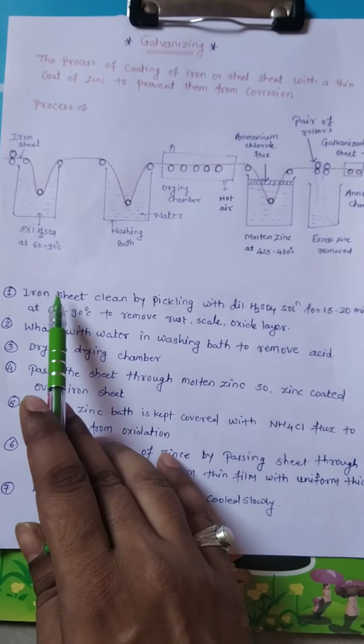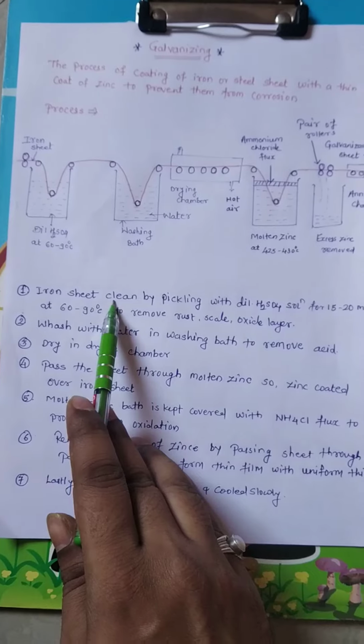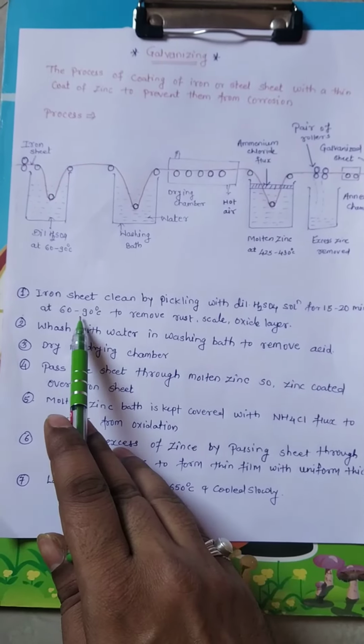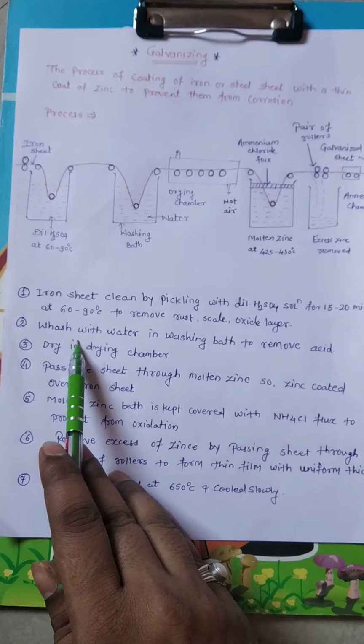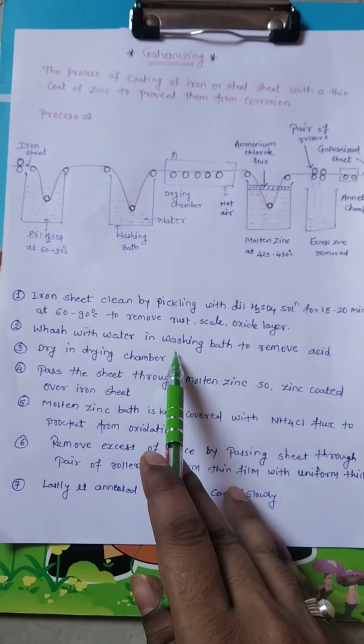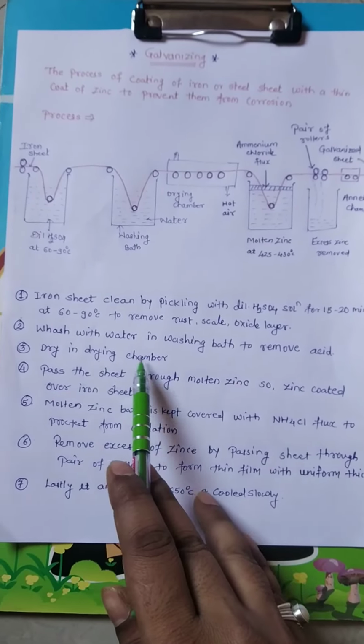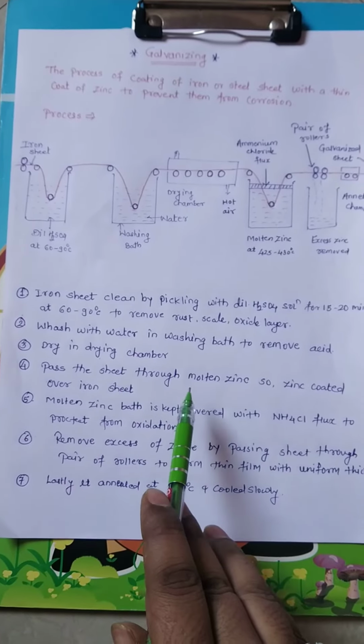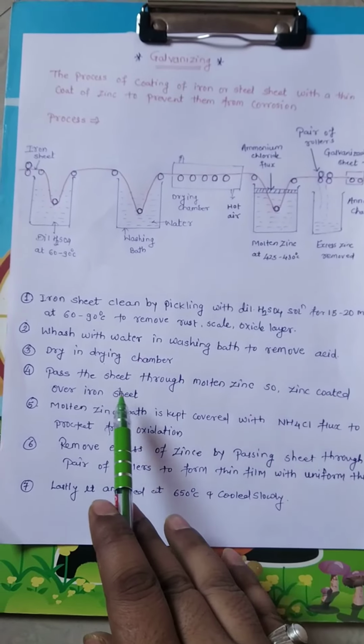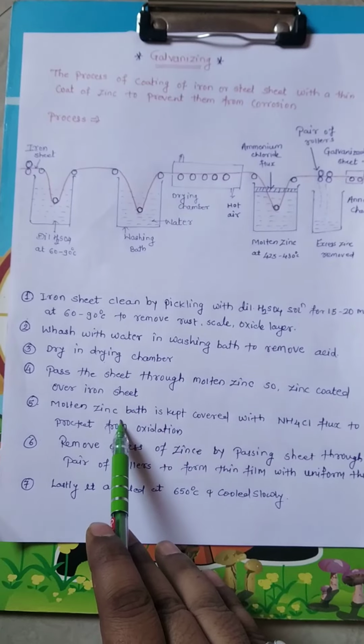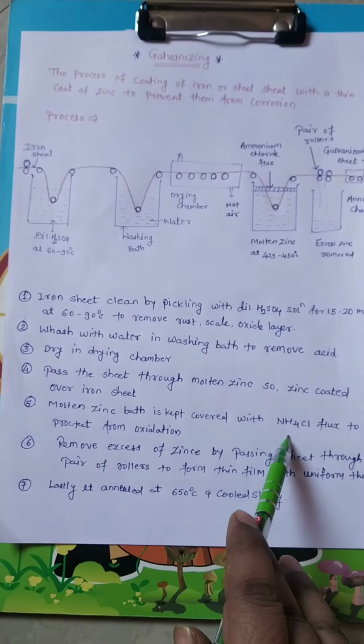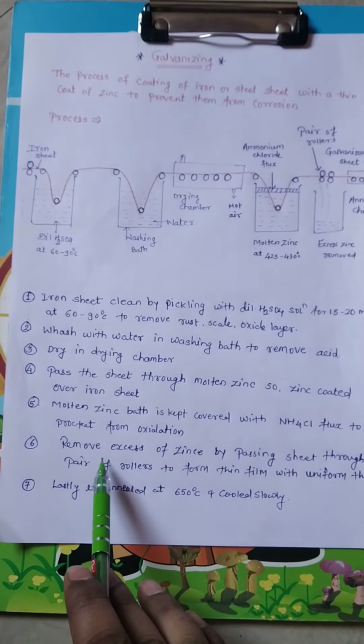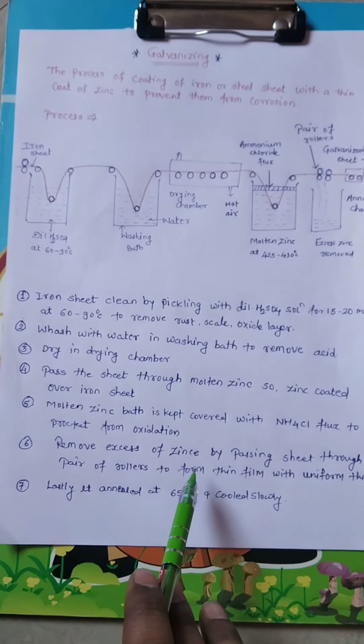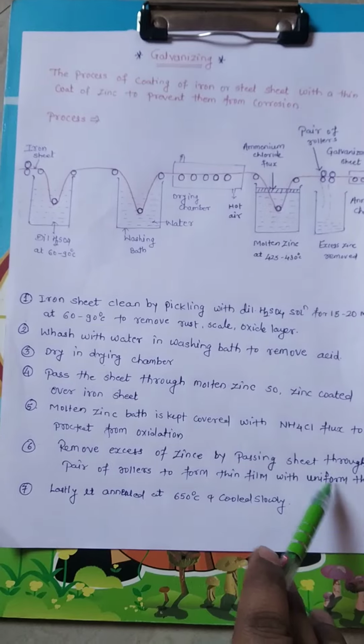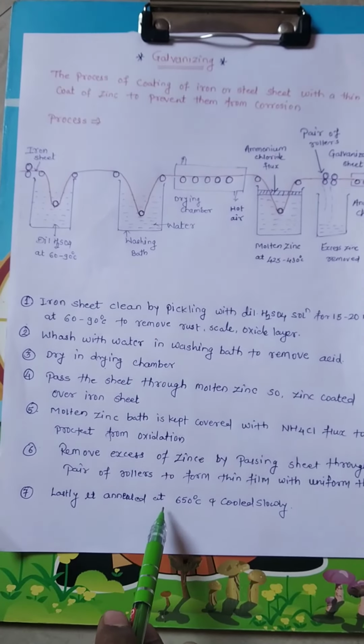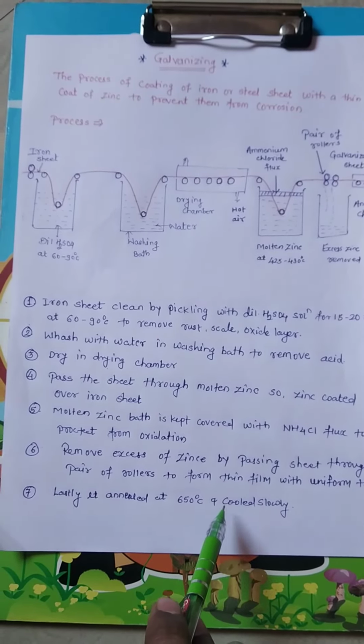So what are the key points? First we carry out the pickling process at 60 to 90 degrees centigrade. Then wash it with water in a washing bath, then dry in a drying chamber, then pass it through molten zinc so that zinc is coated over the iron sheet. The bath of molten zinc is covered with ammonium chloride flux to prevent oxidation. Remove the excess zinc by passing it through rollers to form a very uniform thickness. And lastly, it is annealed at 650 degrees centigrade and cooled slowly.